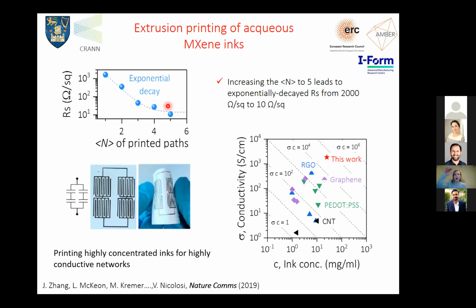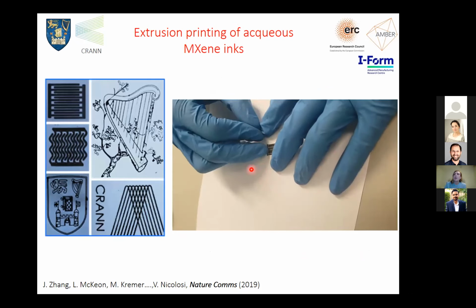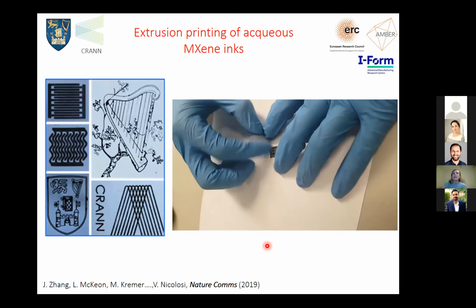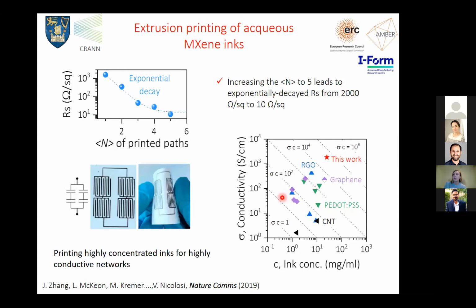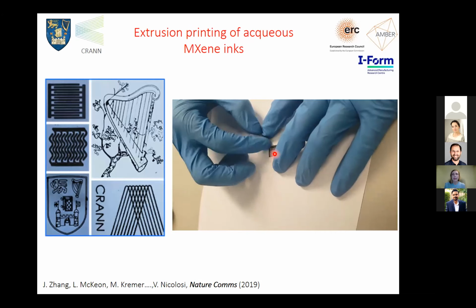With only 5 passes of printing again, we managed to get the resistance really down. Here is the conductivity as a function of the ink concentration, and here is the type of conductivity that our inks achieved. In this video, I also like to play it because you see how sturdy the devices are once they're printed. In this case, we used Scotch tape to peel off a device after it was printed, and no matter how many times we did it, it always came out clean. So we were not easily damaging our devices. They're quite sturdy and very good.